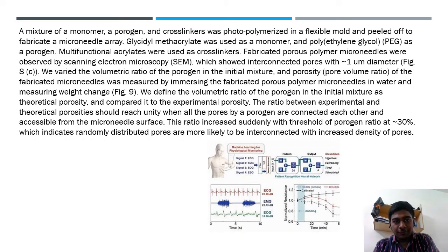A mixture of a monomer, a porogen and a cross-linker was photopolymerized in a flexible mold and peeled off to form a microneedle array. Glycidyl methacrylate was used as the monomer and polyethylene glycol as the porogen. Multifunctional acrylates were used as cross-linker. The fabricated porous polymer microneedles were observed by scanning electron microscopy, which showed interconnected pores with 1 micrometer diameter.